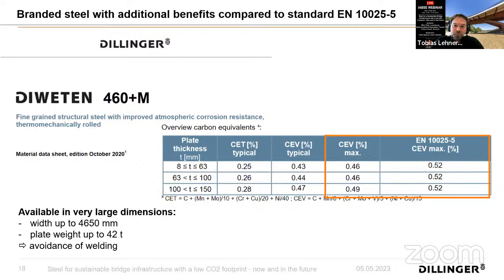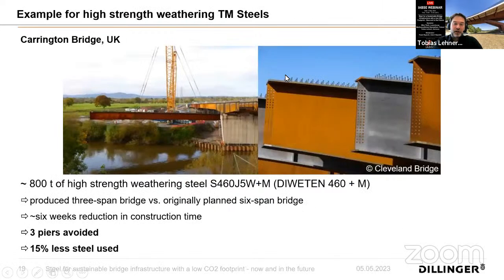So again, better weldability for the fabrication, and it is available in very large dimensions, very wide widths. As with all our plates, we can deliver plates up to 4.6, even 5-meter widths, plate weights up to 42 tons, and that again avoids welding, and by that it is also good for the CO2 emissions and the sustainability. And here's one nice example.